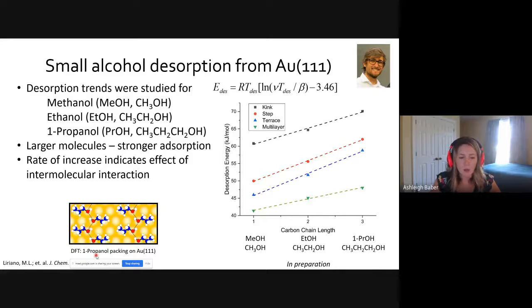And this in particular is 1-propanol on gold 111. He also showed this using STM, but you can see that there is this hydrogen bond interaction on a gold surface that anchors these molecules in place. And there is an interaction between the carbon chains of these alcohols. So all of these alcohols are lined up, and so there are intermolecular interactions between these molecules. Now, if you have a molecule sitting on a terrace site, then you'll expect these types of interactions.